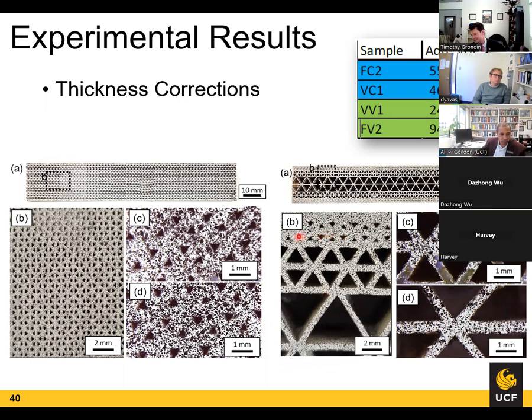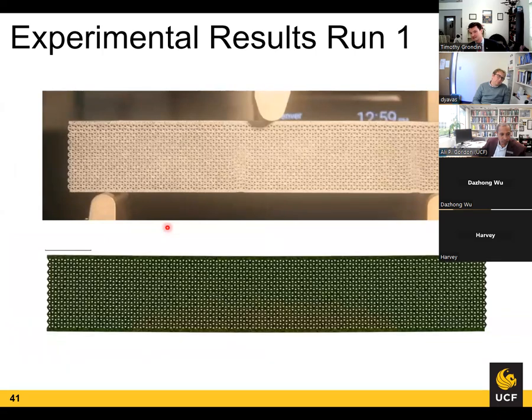That increase of 40% was factored in for the functionally graded system, as well as the massive increase in not only material, but strength of this item, which was skewing our results. We took those increases in cell geometry, converted that to the volume, converted that further to the increase in density, and then the change in the Young's modulus for the core material. Right here you can see the first run coming out.